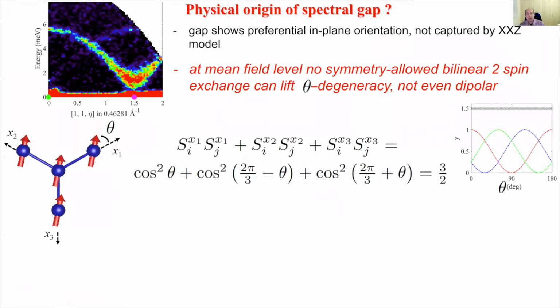So now in the remaining time, I want to discuss the possible mechanism for the gap that we observe at low energies, which indicates a preferential in-plane orientation of the spins that's not captured by the parameterization in this XXZ model that we've discussed so far. So what's surprising is that at the mean field level, no symmetry allowed bilinear exchange can lift this degeneracy, not even dipolar couplings. And let's consider, for example, a symmetry allowed exchange that would prefer, say, for this bond, for the spins to be aligned along the bond direction.